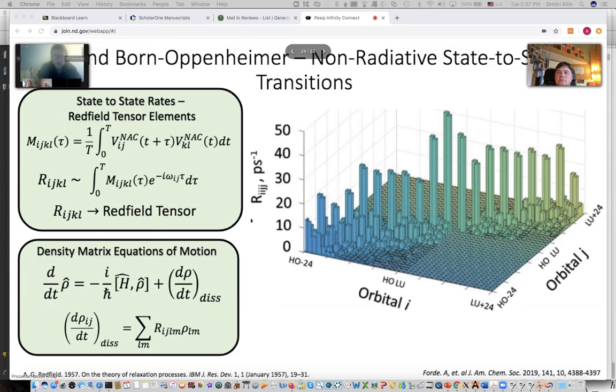And this R term is what we refer to as the Redfield tensor, which is named after the person who first wrote down and solved these equations for a couple of charges and nuclei. And so this Redfield tensor is visualized in this right figure. So the x and y axes are orbital I and orbital J. They refer to electronic states. And then the z-axis represents the rate of transition between orbitals. And so this leftmost block describes transitions within the valence band. And this rightmost block describes transitions within the conduction band.